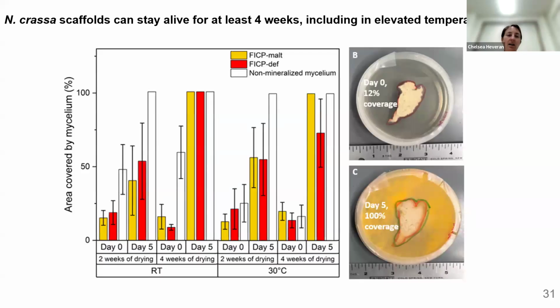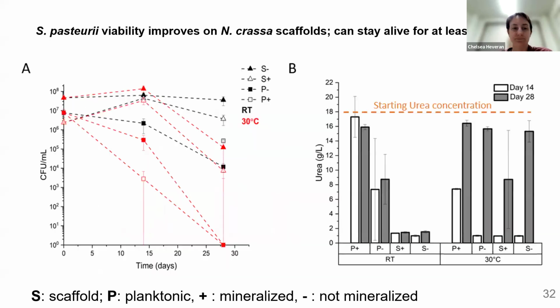It was exciting to us that our scaffold stayed alive for a long time, very robustly alive. So here we asked if living scaffolds could stay alive if we mineralized them, and the answer was absolutely. We measured this by letting it dry for 2 or 4 weeks at room temperature or 30 C, then giving it new food and seeing if it grows. We measure that by the percentage of a plate that it grows over, and everything grew. So our living scaffolds are able to stay very robustly alive for a long time.